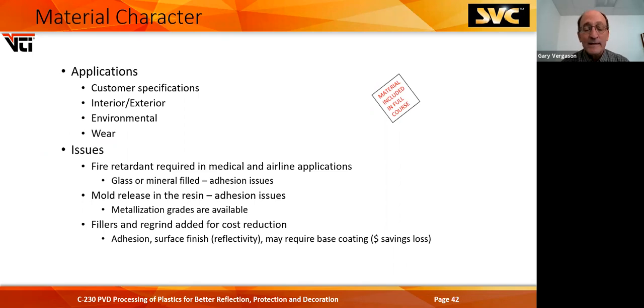regrind's a bad one. You want to reduce the cost, so you reuse the parts that you molded that are bad. They throw them in a grinder, grind them back up, and feed that back in with the resin. Sometimes some customers will use as much as 20% regrind. You're going to see that in the finish of the part. You can't mold the part as smoothly in the case of polycarbonate as you could with the virgin material.